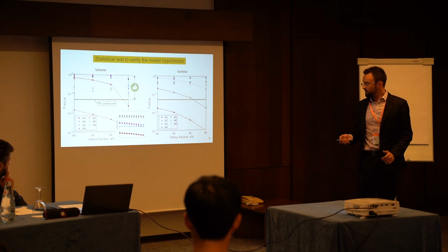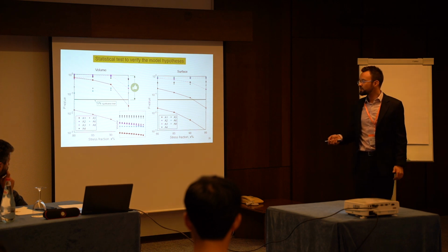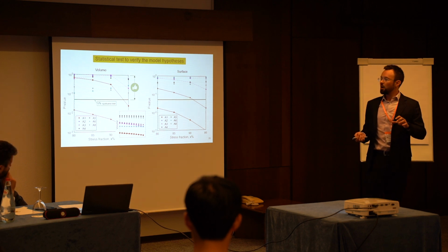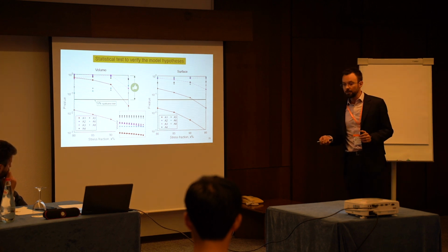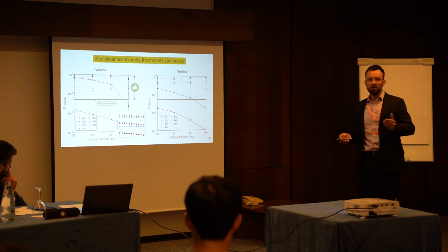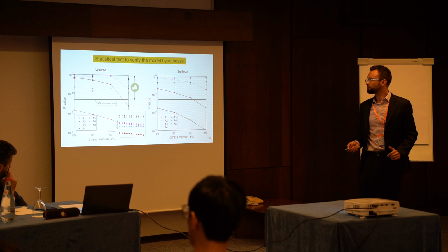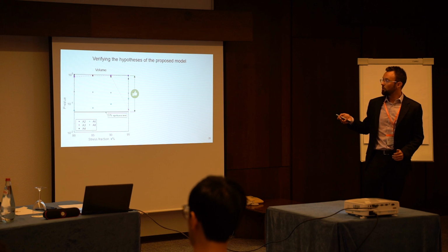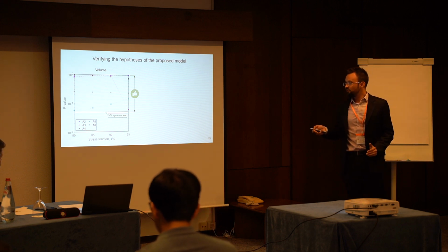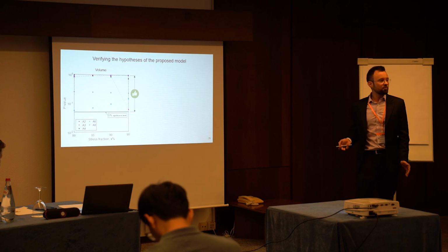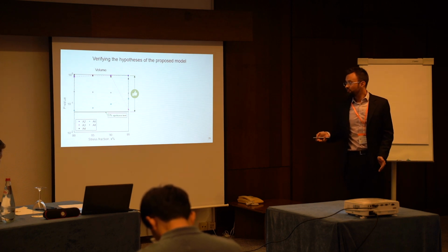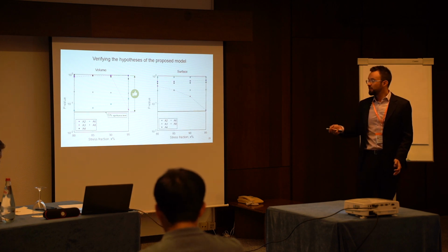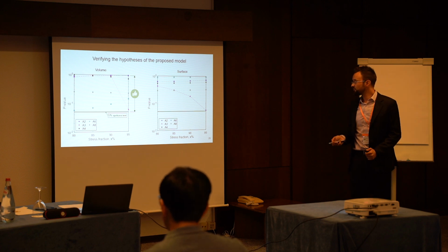And also, if you remember, we can see that the A1 and A5 series all have very small volumes. That's why it might be below a sort of threshold. And here is our test case verifying our model without A1 and A5. We can see that all values are above the 5% significance level for any stress fraction. And here for the case of surface, the same.